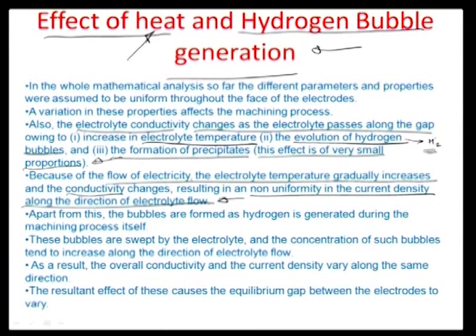Apart from this, the bubbles are formed as hydrogen is generated, as I already talked about, during the machining process. Another big problem is that, let us say the hydrogen starts generating at the entry of the equilibrium gap. So, a larger amount of hydrogen would be packed onto the flowing electrolyte as you go towards the end. So, there is a gradient even in hydrogen. Hydrogen is generated, to begin with, at the entry, and where will this bubble go? It will flow along with the electrolyte. So, at the next instance, when the electrolyte meets another fresh part of the surface where it is doing some machining, more hydrogen is packed in. And so, the hydrogen concentration keeps on increasing as the electrolyte flows past the gap. That gradient also results in a differential change in the conductivity and a differential change in the machining rate, the material removal rate, and is certainly not good for the uniform behavior of the ECM process.